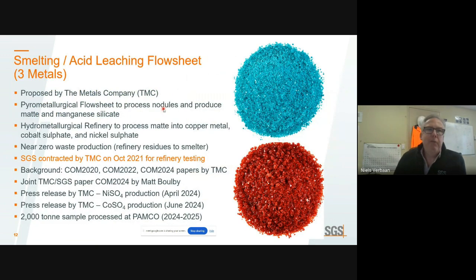Okay, so starting with the first one, this is the smelting acid leaching flow sheet that's been proposed by the metals company TMC. It includes a pyromet processing step to process the nodules and produce a matte and then a manganese silicate. So that's the outlet for manganese within the flow sheet. It uses a refinery to process this matte into copper metal, cobalt sulfate, and nickel sulfate. It claims to be a near zero waste production. And with that, I mean that the residues from the refinery are recycled back into the pyrometallurgical flow sheet.